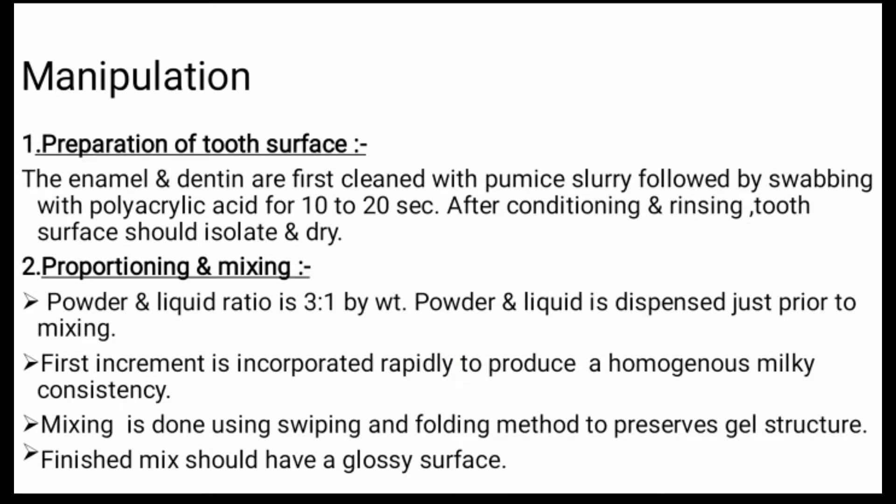For manipulation, the enamel and dentin are first cleaned with pumice slurry, followed by swabbing with polyacrylic acid for 10 to 20 seconds, which is called conditioning. After conditioning and rinsing, the tooth surface should be isolated and dried.